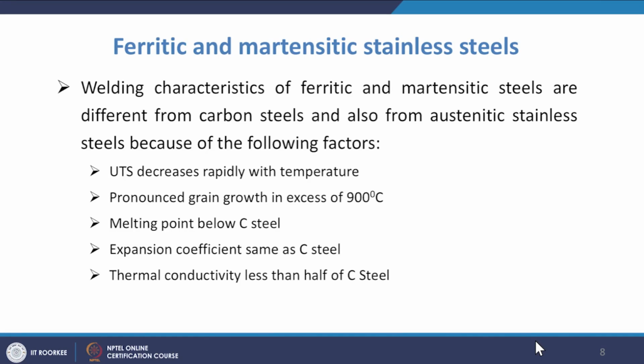So next, coming to the ferritic and martensitic stainless steel. In this case, welding characteristics of the ferritic and martensitic stainless steels are different from the carbon steels and also from the austenitic stainless steel, because of the following factors. Ultimate tensile strength decreases rapidly with temperature, and pronounced grain growth occurs in excess of 900 degrees centigrade. Okay, melting point is below carbon steel, and expansion coefficient is the same as carbon steel. Okay, thermal conductivity is less than half of the carbon steel.